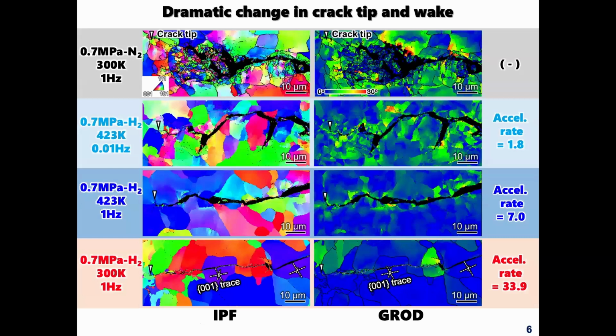The EBSD characterization results made on the cross-section of the CT specimens are shown here for the highest temperature with different loading frequencies, as well as the lowest temperature, 300 Kelvin, room temperature, together with their acceleration rates. The high GROD value around the crack wake became apparently smaller along with increasing acceleration rate.